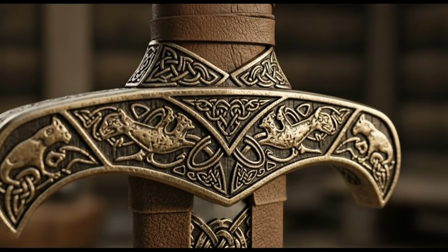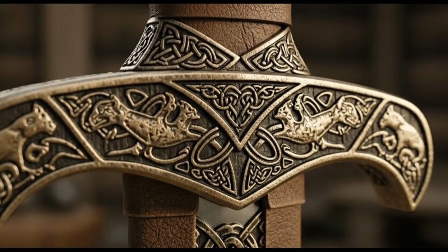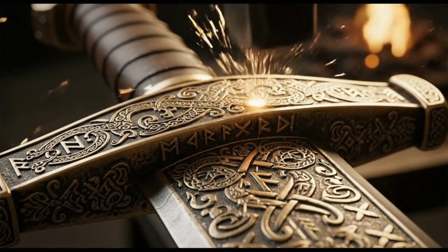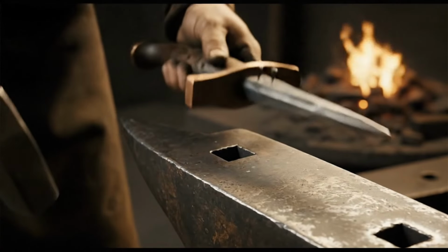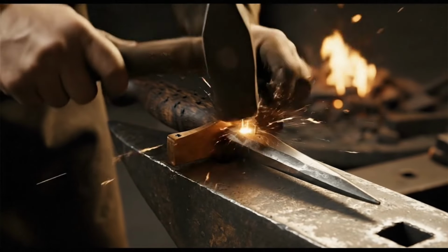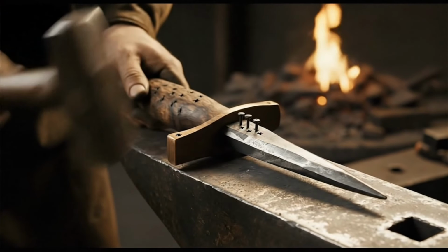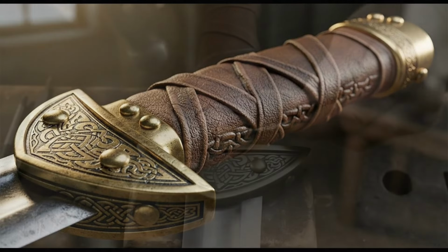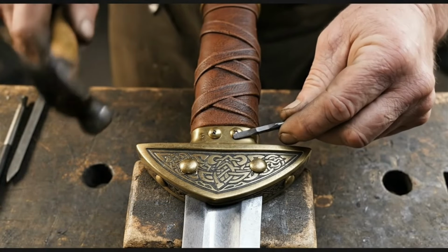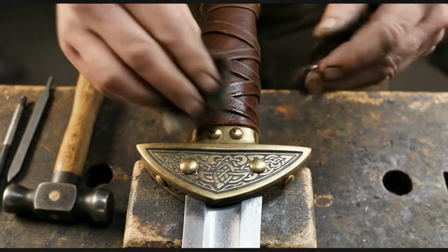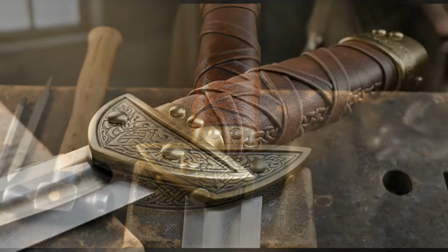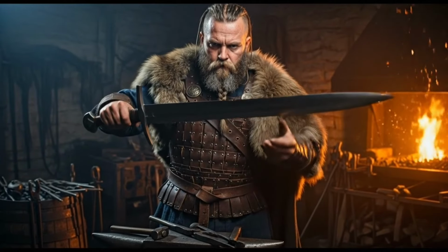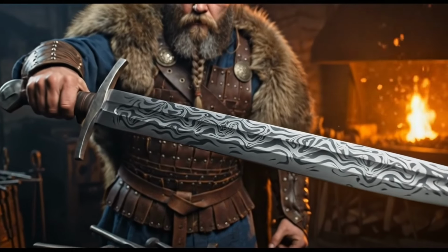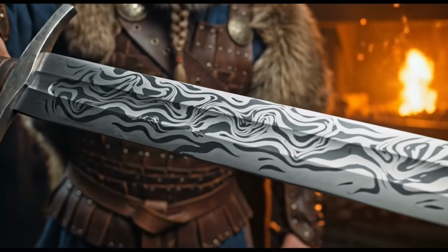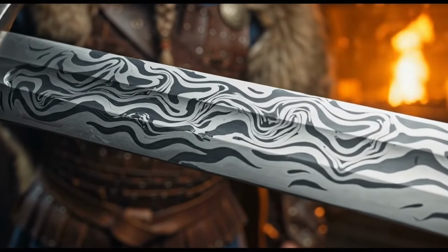Metal strips were heated in chambers to welding temperatures and fused together using forging methods, hammering them into singular rods. These rods were then reheated and twisted along their axes like cordage. Twist quantity and direction depended on desired designs. After twisting, rods were flattened again. Frequently, 2 or more twisted rods were welded together, creating even more intricate designs. This procedure repeated numerous times until the master obtained the central portion of the future blade.